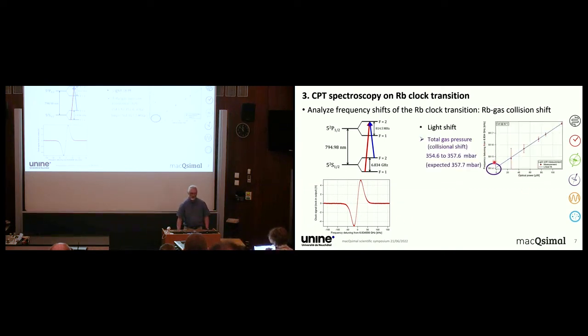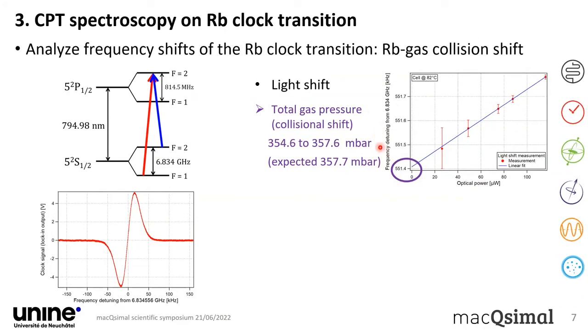Now, this frequency that we measure here, that we plot vertically here, unfortunately is sensitive to light shift, which means if we vary the optical light intensity here, we get some dependence of the frequency. So, of course, we need to correct for this, and we extrapolate to 0 light intensity in order to conclude on the light-shift-corrected collisional shift of the rubidium transition, and from this we can get information on the total gas pressure, and we find values between 350 and 358 millibars, which is right close to the expected 357.7 millibars due to the mixtures we put inside.